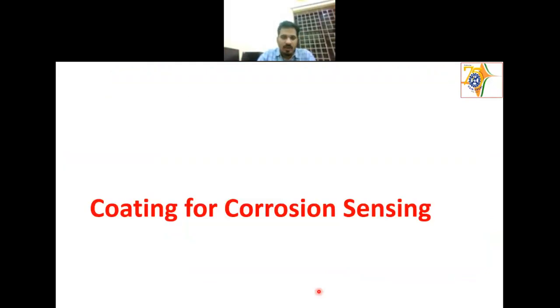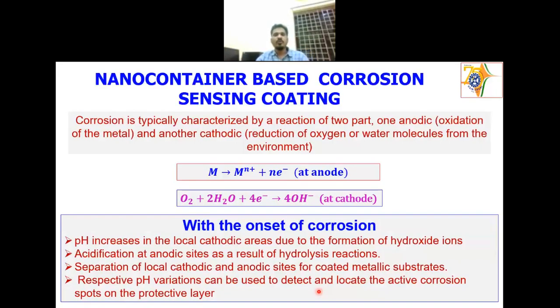Now that we have finished the conducting polymer part, we'll move on to another topic, corrosion sensing. We all know that corrosion is typically characterized by a reaction of two parts: one anodic part, the oxidation part, and another cathodic part. With the onset of corrosion, what changes happen? The pH increases in the local cathodic areas due to the formation of hydroxyl ions. There is acidification at the anodic site as a result of hydrolysis reactions, where H plus ions come. So local anodic and cathodic sites are formed here. The respective pH variation can be used to detect and locate active corrosion spots on the protective layer.